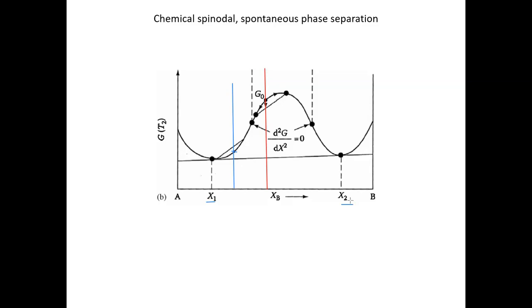Now, if we do a similar analysis, say we start from a mixing state. Let me change notation. So if we start from a mixing state, this is X naught, right? And then you have these two separate states, with a slightly lower and a slightly higher composition. Initially I'm right here. Now I follow the same consideration. Suppose I have a fluctuation to reduce the composition a little bit and to increase the composition a little bit. Now I use the same analysis to see how a spontaneous fluctuation changes the free energy. Does this lead to an increase or decrease? Following the same analysis, we can immediately see that if the fluctuation leads to slightly different compositions, you immediately increase the free energy. So this is for small fluctuations.